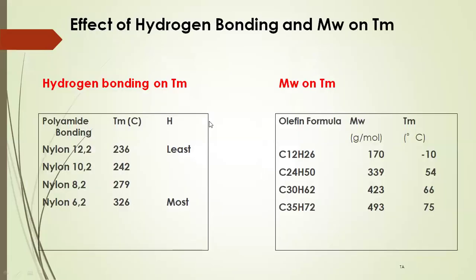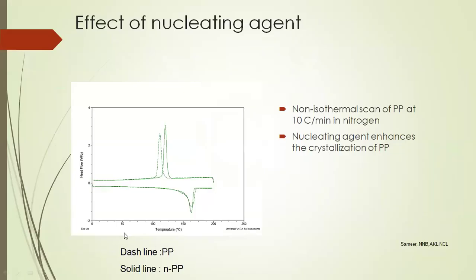What are the factors that affect the melting? Again, hydrogen bonding. Your melting increases with hydrogen bonding. If you increase the molecular weight, your melting again increases with molecular weight. You know, many times the processor adds fillers in our material. We have seen PP filled with filler. So if PP is filled with filler, what is its effect? It affects the crystallization. Filler will not affect melting of the polymer, but it affects the crystallization of the polymer because the filler which you have added acts as a nucleating agent for the polymer. It enhances the nucleation, and the polymer crystallizes at a higher crystallization temperature.